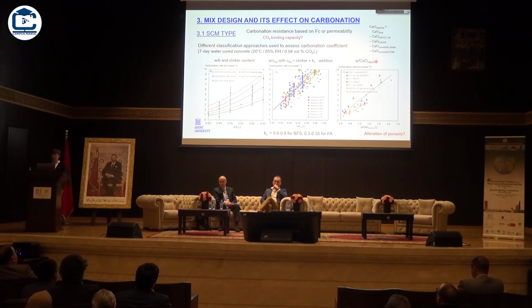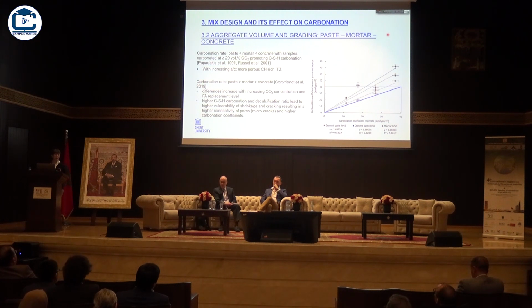And then a third way to consider this is to plot the carbonation rate against water over the reactive calcium oxide in the mix, which also gives a reasonably good correlation. It's maybe the most scientific approach because you really look at all the calcium oxide that can react, not only in the portlandite but also in the CSH. So it's actually the total calcium oxide, but you have to subtract the calcium carbonate that is initially present, and then also calcium oxide in calcium sulfate and unreacted clinker and SCMs. But that does not take into account changes in porosity, of course. So it's also not a complete picture that you get in this way.